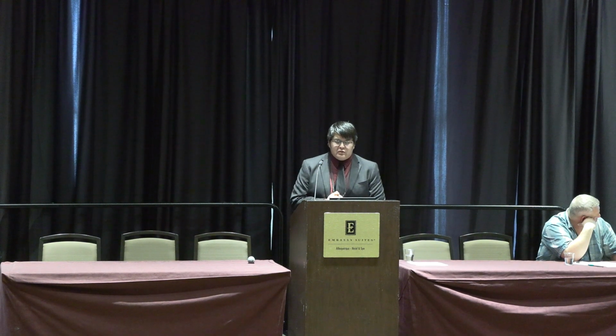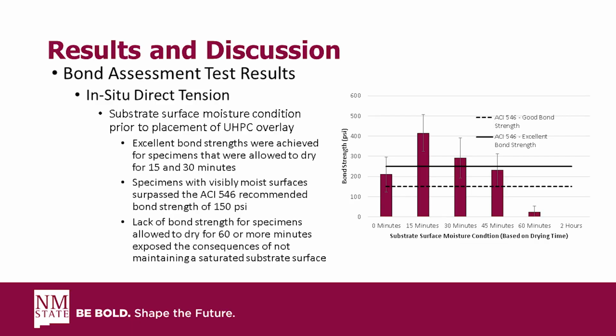Now going into the actual results for the bond assessment test, starting off with the surface moisture conditions. So a little bit about this plot here. You see two lines, a dotted line and a solid line. The dotted line is going to be ACI 546 recommendation for a good bond strength of 150 PSI. And that solid black line is ACI 546 recommendation for excellent bond strength of 250 PSI.